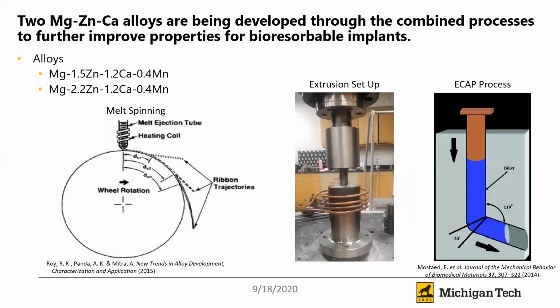So I will be developing two magnesium, zinc, calcium alloys with trace amounts of manganese to evaluate the mechanical properties and corrosion behavior of these alloys after they have gone through the melt spinning process, which will produce magnesium, zinc, calcium ribbons. And then these ribbons will be consolidated through hot extrusion.